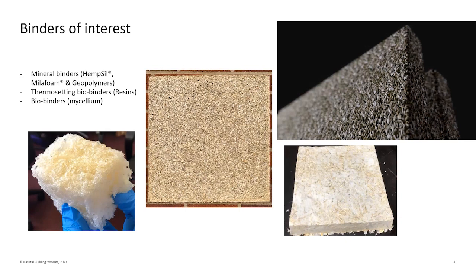And a geopolymer, which is like a cement, but a lot less carbon involved. And you can actually manage the way it dries and sets much more readily. And then thermosetting binders, we're working on a bio-based thermosetting binder. This is some material that we've developed, which uses a thermosetting binder, which contains no VOCs, no formaldehyde, no petrochemicals. And then we are going to also be looking at bio binders, mycelium, but that's a little way in the future.